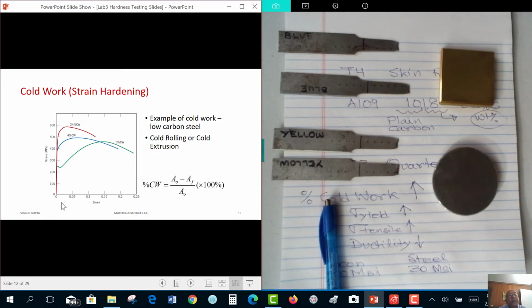So you can see by the process of cold working, cold rolling, cold extrusion, cold forging, we can make a material stronger. But the price we pay, you can see right away, is in ductility. 0% cold work has high ductility. This blue one, which is 4% cold work, lower ductility, and the red one has the lowest ductility of them all.